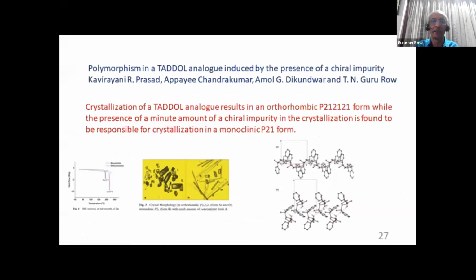One example from our literature, where I've mentioned at the beginning that sometimes the addition of impurities can generate new polymorphs. One of the very startling examples is the case of TADDOL. The compound TADDOL actually crystallizes in a space group P212121, shown in terms of this kind of morphology. And in the presence of a chiral impurity, we added a small little chiral impurity, we see that the crystallization is found to be responsible. The appearance of the chiral impurity crystallizes in a different form.